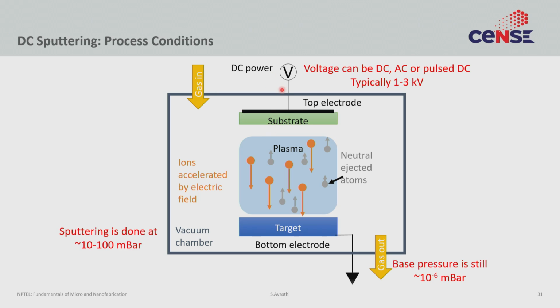So you apply a DC bias, typically 1 to 3 kilovolt. And this can be DC, it can also be AC, that is called RF sputtering. We'll talk about that later. It can also be pulsed DC sputtering. In fact, lately there is an emergence of a new type of sputtering system which is called high impulse magnetron sputtering. We'll not talk about it, but DC or pulsed DC would both work. The pressure maintained inside the chamber typically is between 10 to 100 millibar. As we shall see, this pressure range is critical for self-sustaining plasma.